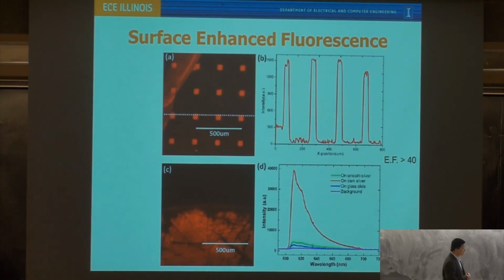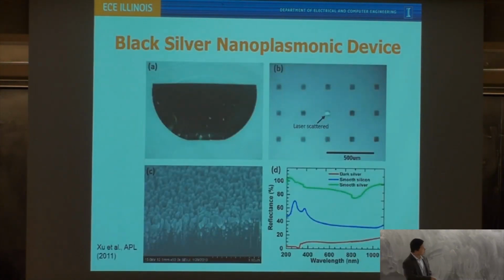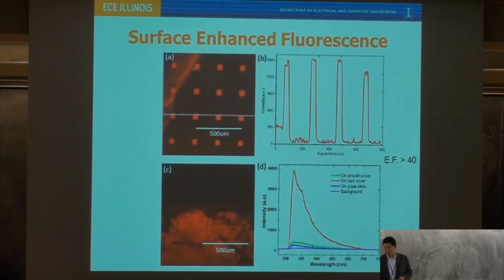Here's a demonstration of surface enhanced fluorescence. We're not getting beyond the surface yet. The fluorescent molecules are directly spread out on top of the surface, so they have physical contact with it. On a device like this, as I said, we have nanostructure inside a square and a smooth film outside the squares, so we can do a fair comparison of intensities on the same substrate. You can see a much higher fluorescent intensity inside the squares compared to outside.